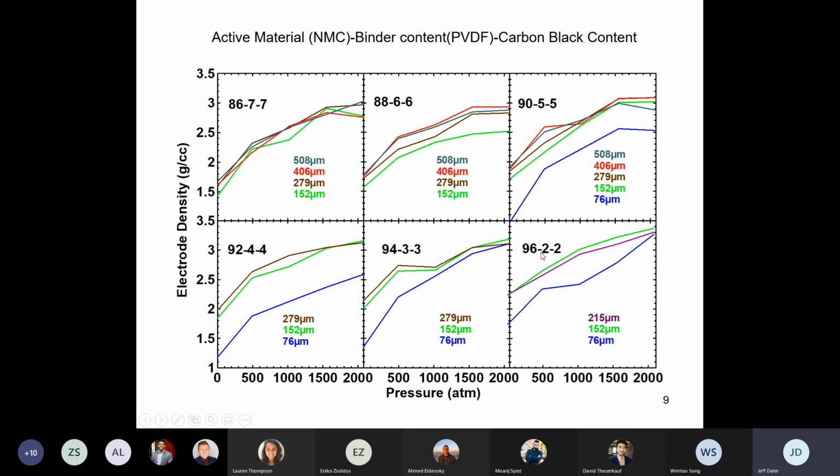But the carbon black and the binder each take up some space. So the porosities in these kind of heavily compressed electrodes are somewhere around 25% or so. The pouch cells that we get from Li-Fun, typically the positive electrode compression is around the same place, around 3.3 grams per centimeter cubed, just for your interest.